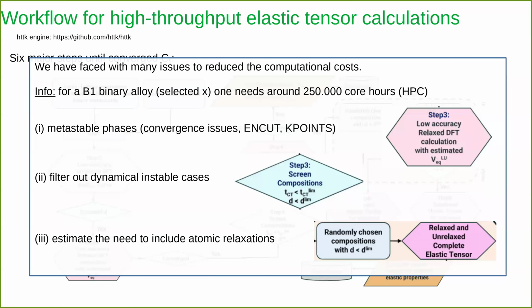And then in case you want to have it for several concentrations, close to dynamical instability where the elastic constants can be engineered very nicely, then you can forget about this type of workflow. You need to make some changes, and this is what we suggest here. So we suggested two major steps to consider.